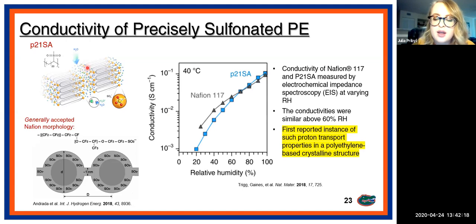So in this work, our group and the Winey group compared Nafion 117 with the P21SA polymer at a range of relative humidities. So at relative humidities above 60%, the ion conductivity was right on par with Nafion. And this is the first reported instance of such proton transport in a polyethylene-based crystalline structure. So this was a really big achievement in using the secondary structure of a precision polymer to prepare something that can do some work for us.